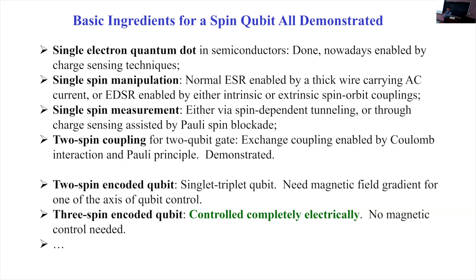Okay. And two-spin coupling, as I mentioned, is actually pretty strong. So people actually don't want to go to the large coupling limit because the electronics that are available now are just not fast enough to deal with really strong coupling. But it's definitely already demonstrated. Okay. And even further, beyond the single spin encoding of a qubit, as in the original Loss-DiVincenzo proposal, people also came up with different ways, for example, encoding a qubit into a two-spin state, singlet-triplet, or into a three-spin state, the so-called decoherence-free subspace, where the control of the qubit state can be done completely electrically using exchange coupling without magnetic pulses. Okay, so you have quite a lot of progress in how to control the spin qubit and measure them.